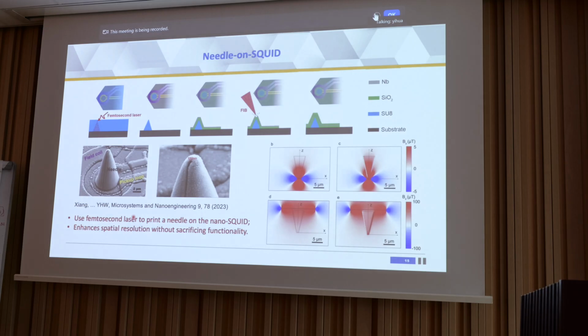And there's also a downside with this kind of technique, which is that the pickup loop is typically very far away from the sample, so the spatial resolution is not optimal. So we have come up with a technique to print a superconducting tip, a superconducting needle, on top of the pickup loops to enhance the spatial resolution without sacrificing the capability to perform flux feedback and susceptometry. We have demonstrated that in principle it works, and we have enhanced the spatial resolution, but we have yet to achieve the optimal spatial resolution, but we are working on this.